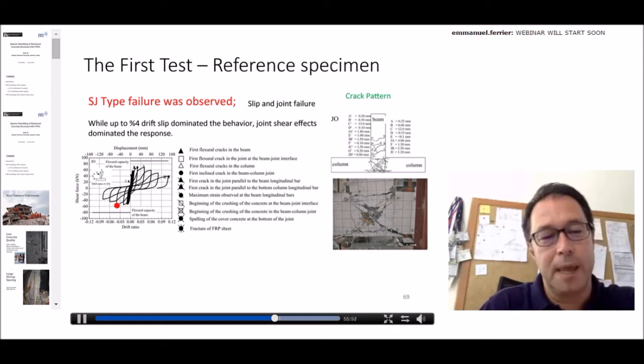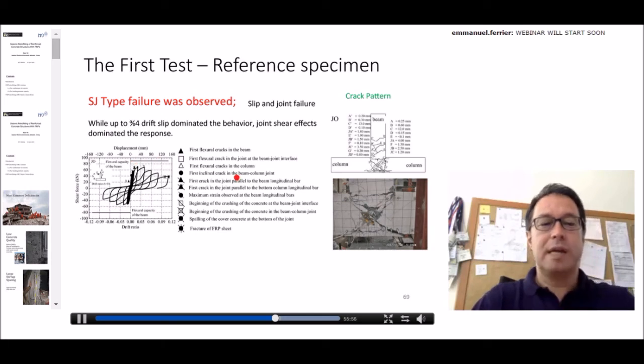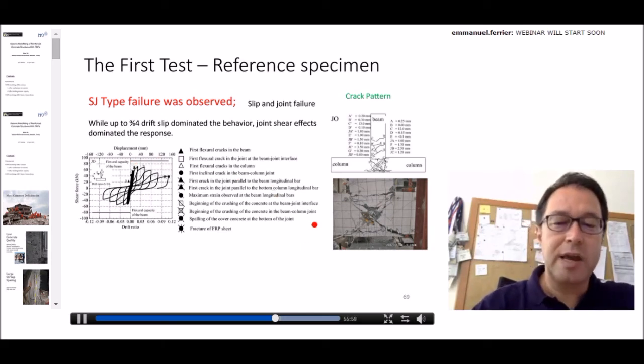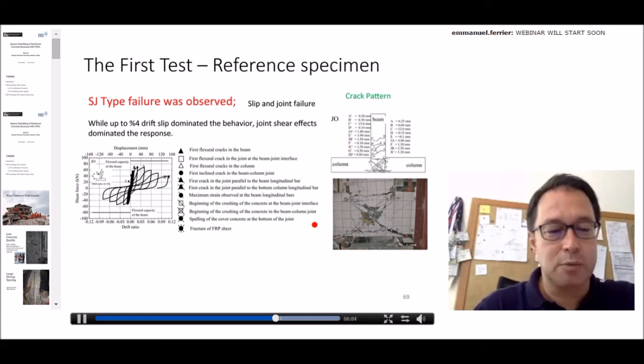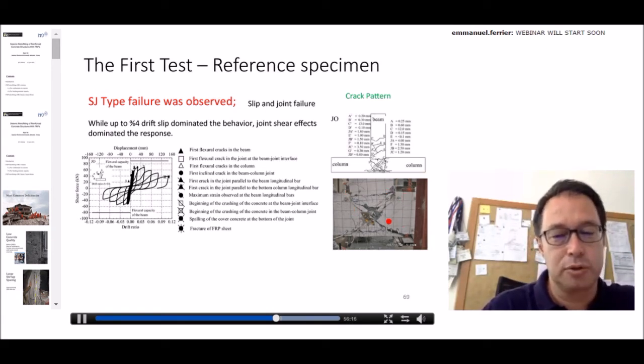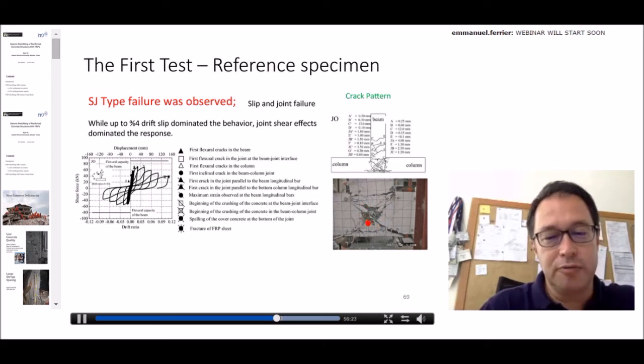This line shows the flexural strength of the beam. I should say that the strength hierarchy for these beam column joints is like that. The reference specimen has weak joints, so the most critical area is the joints. And then if we sufficiently strengthen the joints, then the next weakest member is the beams, and the column is the strongest. So if we don't retrofit the joint, the failure is expected to be because of the joint, as obviously seen with this test result.